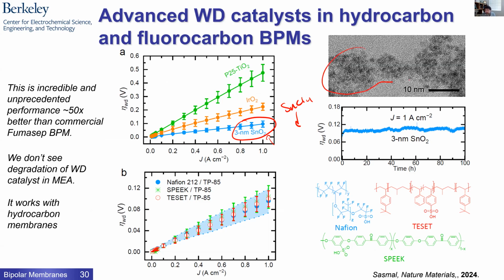So we get these very crystalline particles. You probably can't see them, but you'll see all the lattice fringes if you look closely. Crystalline small particles of tin oxide, and we never have to dry them out or heat them up. So these particles have reasonably high electronic conductivity. We've actually now fluorine doped them, which makes them even better electronic conductors and gives even better performance. And they have a huge number of surface hydroxyl groups because we never had to heat them up and calcine them to crystalline. And these things really scream.